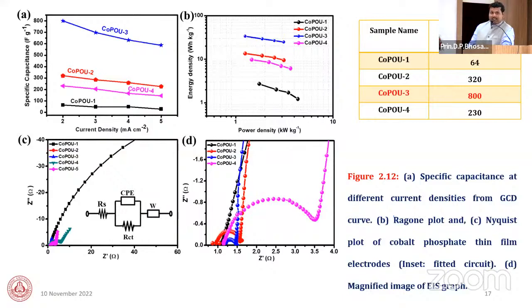Then I did the impedance study, and it also shows that with increasing concentration, the RCT value changes. RCT means charge transfer resistance value, and RS is not only the solution resistance. It is the sum of the solution resistance, electrode resistance, and connection resistance. The RCT value decreases with increasing urea concentration up to the third sample, and again it increases because of the morphology change of the sample.